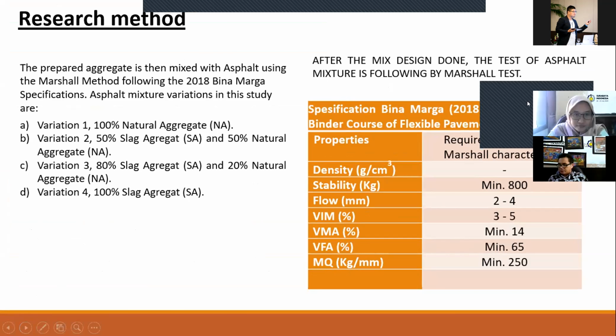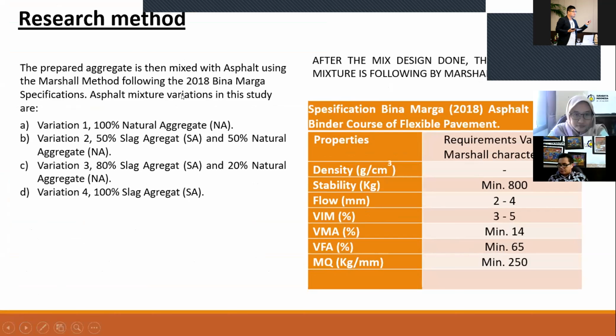In this research method, the prepared aggregate is then mixed with asphalt using the Marshall method following the 2018 Bina Marga specification. The asphalt mixture variations in this study are: variation 1, 100% natural aggregate; variation 2, 50% slag aggregate and 50% natural aggregate; variation 3, 80% slag aggregate and 20% natural aggregate; variation 4, 100% steel slag aggregate.